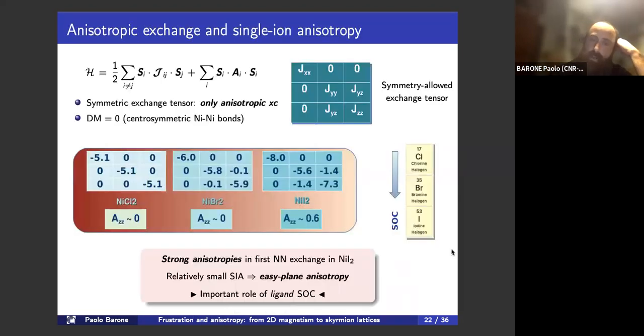So we include the spin-orbit coupling in our calculations, and we evaluate the full exchange tensor alongside the single ion anisotropy. And the first thing to notice here is that because of the edge sharing of the octahedra in the structure, each nickel-nickel bond is centrosymmetric. So it has an inversion center, so there is no Dzyaloshinskii-Moriya interaction in the system. And in fact, from our calculated exchange tensor, we find that the exchange tensor is symmetric.